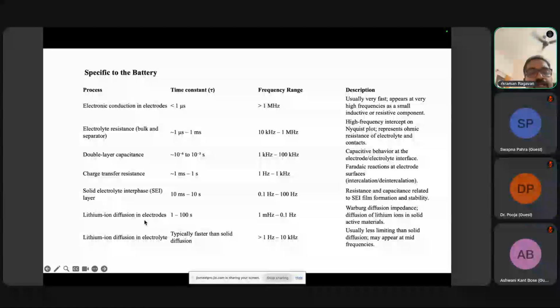So the lithium-ion diffusion into the electrode is the slowest process that you would see in the entire battery. The redox reaction may be faster, but the lithium which is intercalated into the electrode has to move, so that the next lithium comes and intercalates through that window. So that is the slowest process. That happens in the 1 millihertz to 0.1 hertz frequency range. These are typical time constants that you should remember when you are characterizing a battery, because if you see impedance features in this frequency range, you can quickly think it is something related to lithium-ion diffusion in the electrodes and so on.